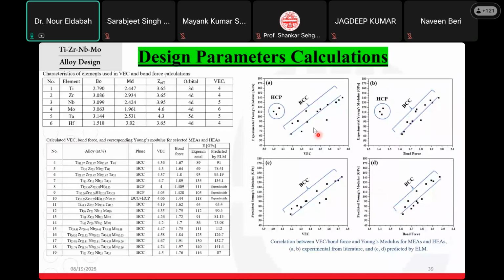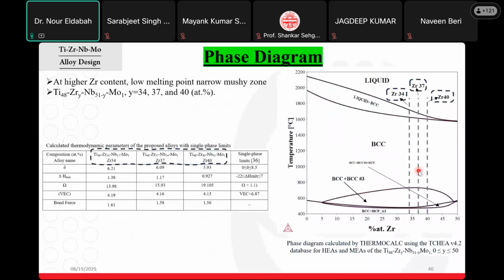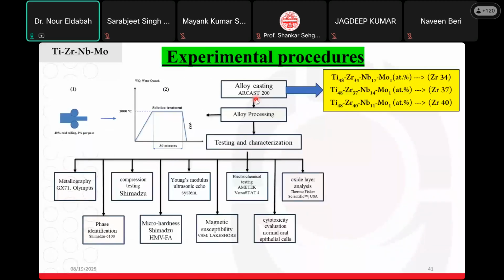That's why we should follow the production of the as-cast state by a solution treatment to stabilize the single BCC beta phase. These are the final compositions, with the calculated bond force all around 1.6 and valence electron concentration around 4.2. For the experimental procedures, as you can see, we make arc furnace casting using the Arc Cast 200, which is the model of the device.